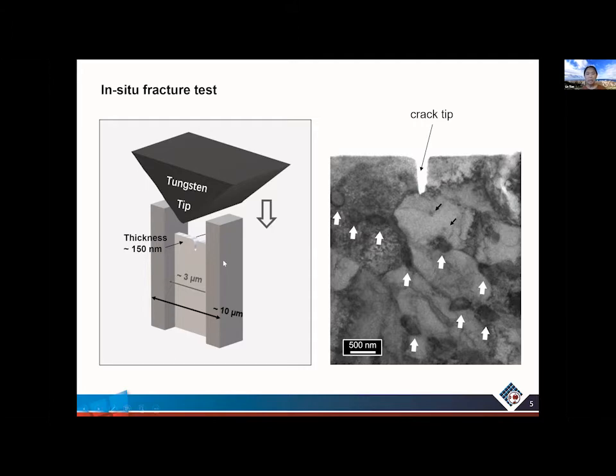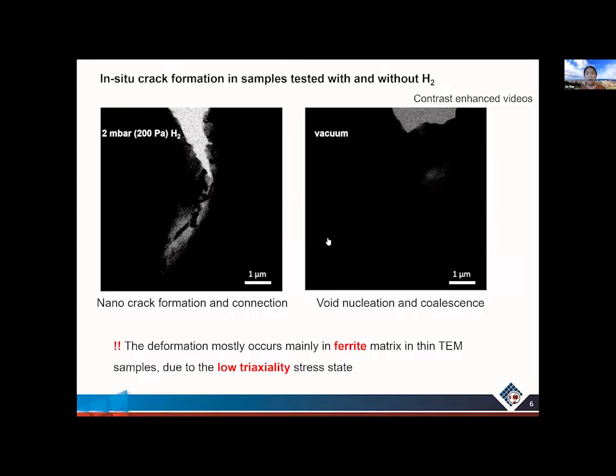Inside a TEM, we use a wedge-shaped tungsten tip, and if we move it downward, it will push these 2 pillars away from each other, and that will create stress on this thin part in the middle. On the right, I show you this TEM bright field image of a sample that we tested. We can still see the microstructures and also the particles and even some dislocations during deformation. For the crack here, this is also cut by focused ion beam to create a preferential site for the crack nucleation.